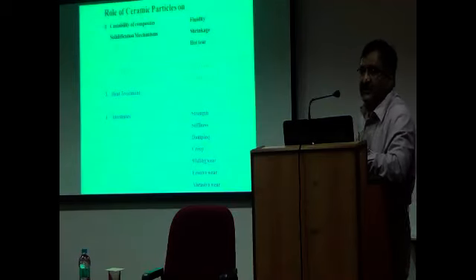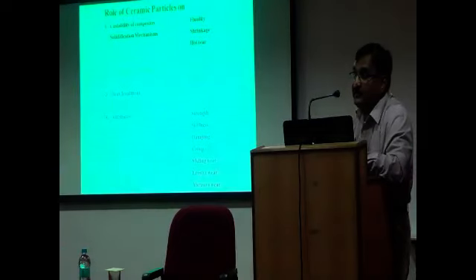Now, when you have these ceramic particles, generally alloys are free from a large volume fraction of coarse particles. In an alloy, for example, steel has some carbides, aluminum has some precipitate particles. But in compositing, we deliberately add 10 to 20% of particles into the liquid metal and produce a composite.